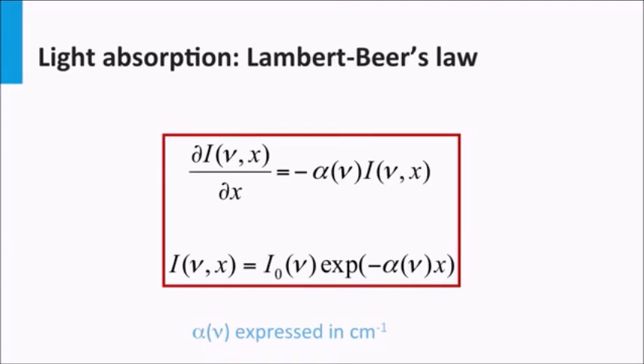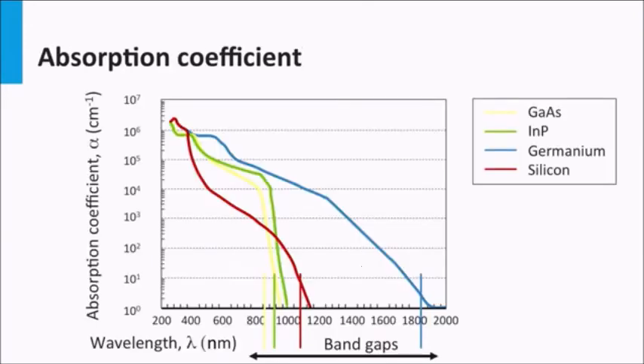It is important to realize that the absorption coefficient for materials is not the same at every wavelength. In this figure, the absorption coefficients for 4 different semiconductor materials are plotted: germanium, silicon, gallium arsenide, and indium phosphide. First, you see that germanium has the lowest bandgap. Germanium starts to absorb at high wavelengths, which means low photon energy. Gallium arsenide has the highest bandgap as it starts to absorb light at the smallest wavelength or the highest photon energy.